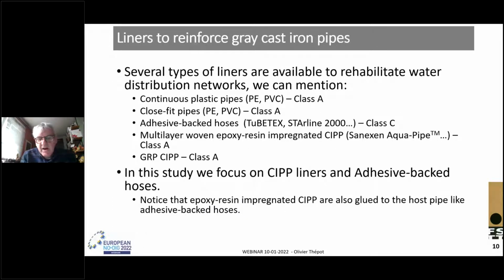Several types of liner are available to rehabilitate water distribution networks. We can mention continuous plastic pipe, PE-PVC, class A; close-fit pipe, also PE-PVC, class A; adhesive backed hoses like Tubetex, Starline 2000, class C; multi-layer woven epoxy resin impregnated CIPP like Sanexen Aquapipe, class A; and GRP CIPP, class A. In this presentation, we focus on CIPP liners and adhesive backed hoses.